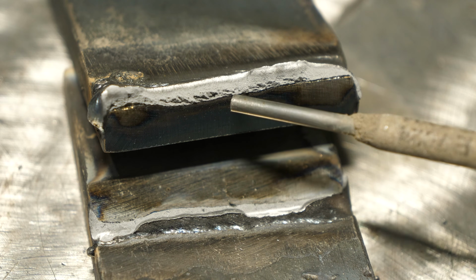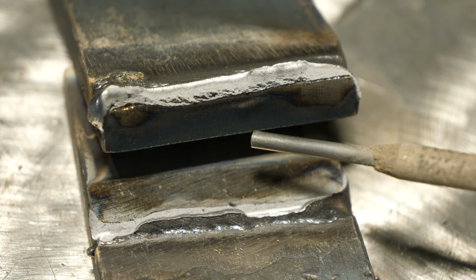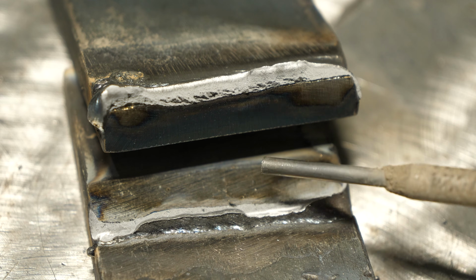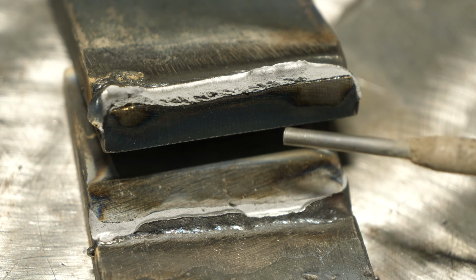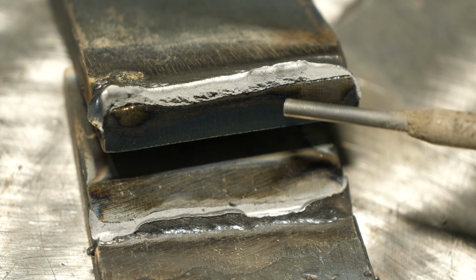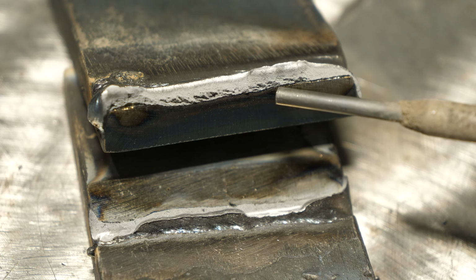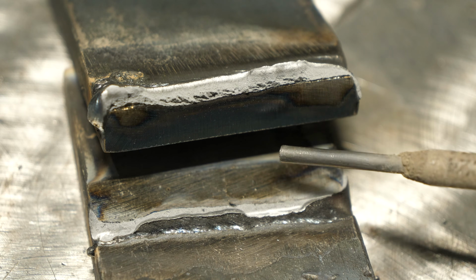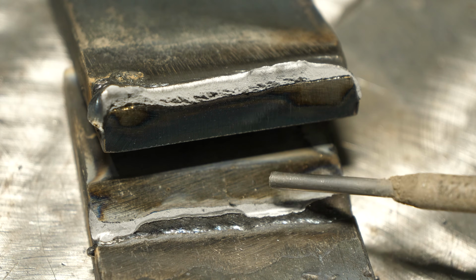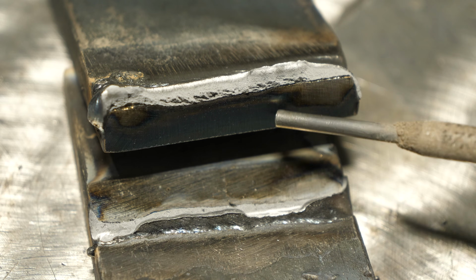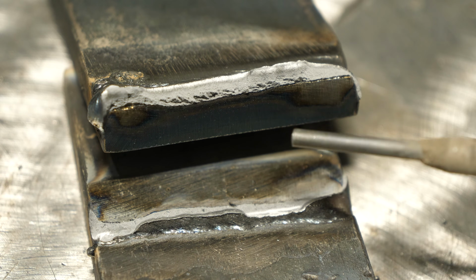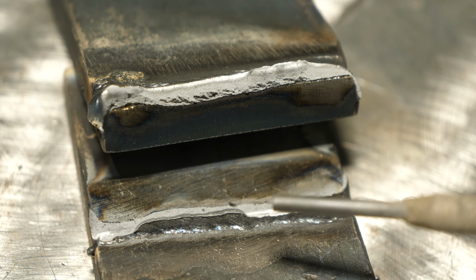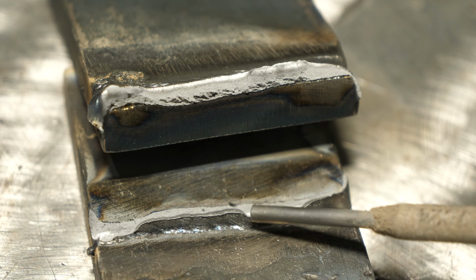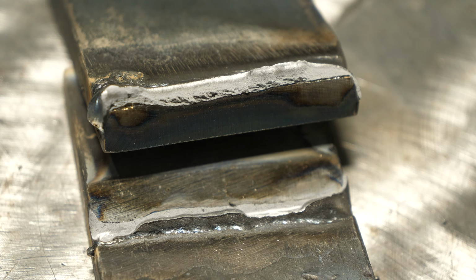The root cause of that is the penetration isn't quite as good as what I would have expected, but it did get in there, and the results, I would say, are on par with 70-18. Believe it or not, ER70 MIG actually does exceptionally well on this, on a 200 amp MIG welder on this 3/8 plate. It actually surpasses the strength of this rod and 70-18 on a bend towards the face. So pretty interesting. Now, what's even more interesting is how these other ones failed.